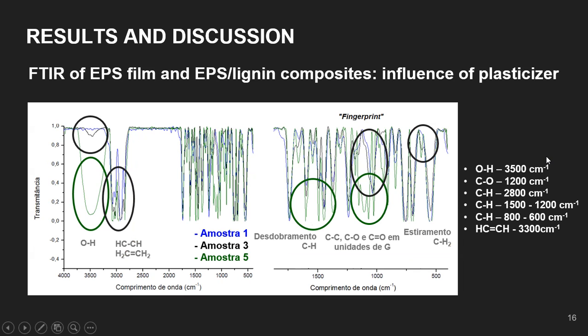Now, observing the overlap of the FTIR spectra of composites. When comparing the spectrum of sample 3, with 5% lignin, with sample 1 of pure EPS, a small hydroxyl band around 3,500 cm, circled in black, appears. In addition to the development of the band close to 1,200 cm, which probably corresponds to the units of carbon-carbon,